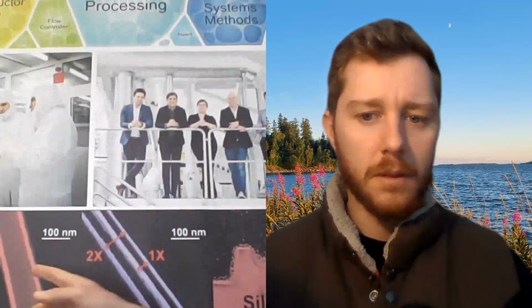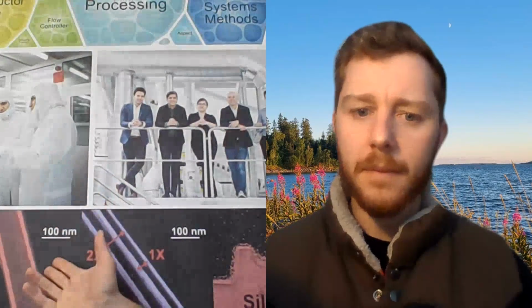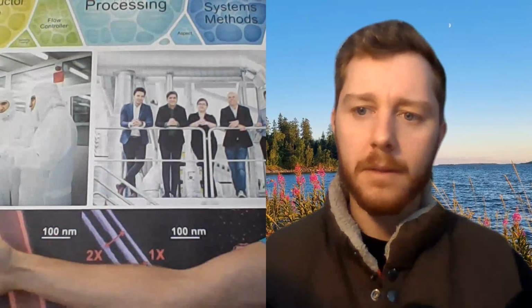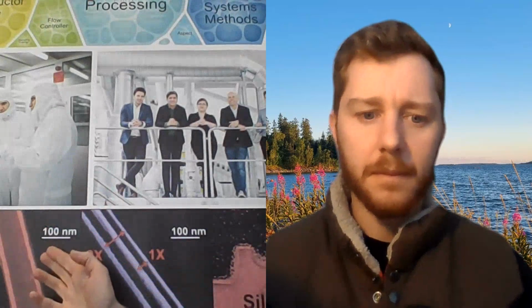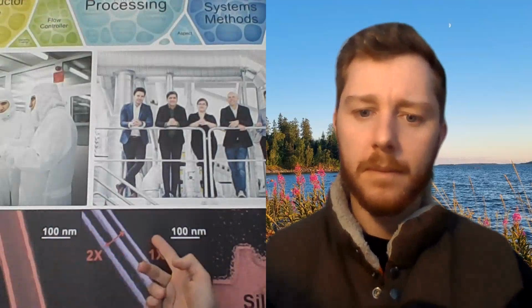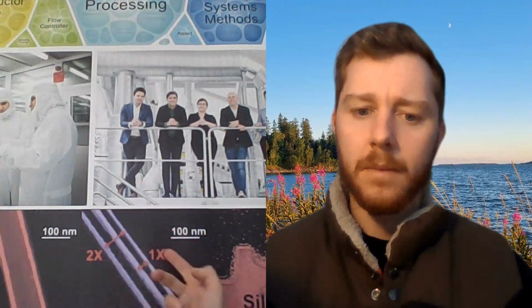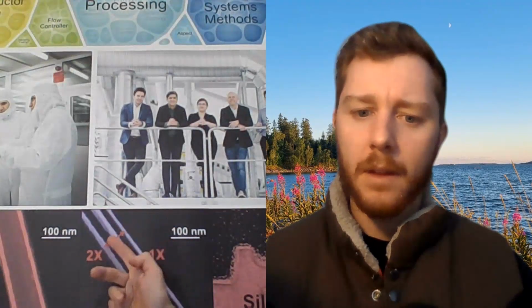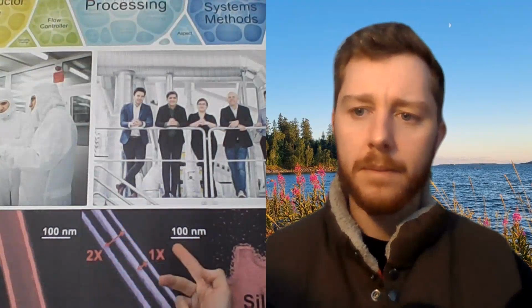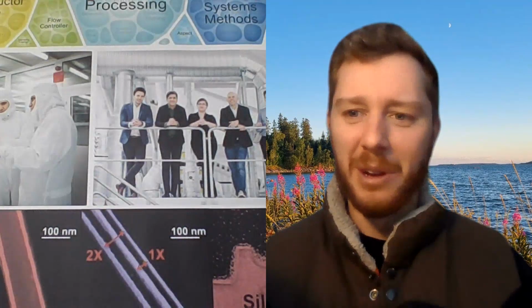And then we tried it on silicon nanowires, about 100 nanometer diameter. We also split it. We thought this was a crystalline effect because these are hexagonal, whereas these are round, but we could also split round nanowires. And we manipulated some samples next to each other, so we could do a pitch split. So here are 2 wires with a 2 times bigger pitch, and we etch both of them and we have half the pitch. That's when we realized that we have a new pitch splitting technology, and we decided to file patents on this.